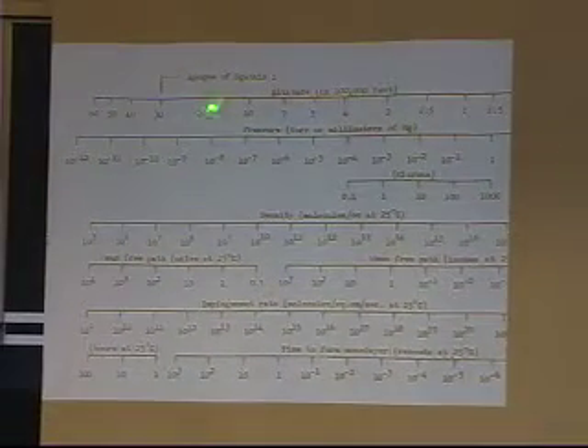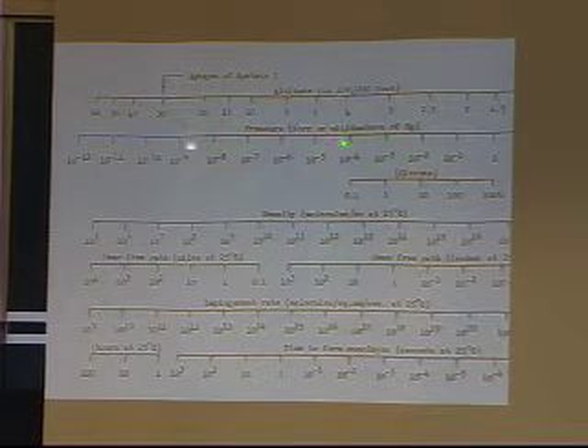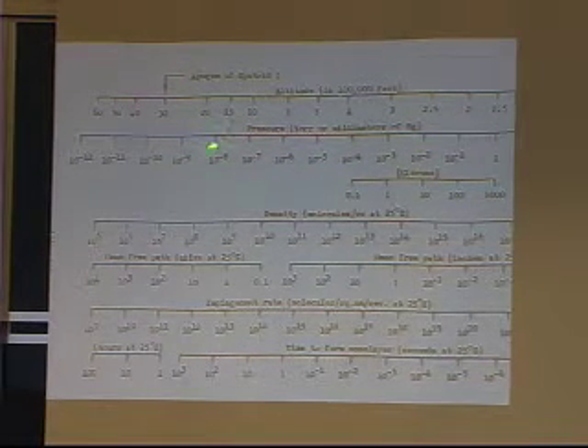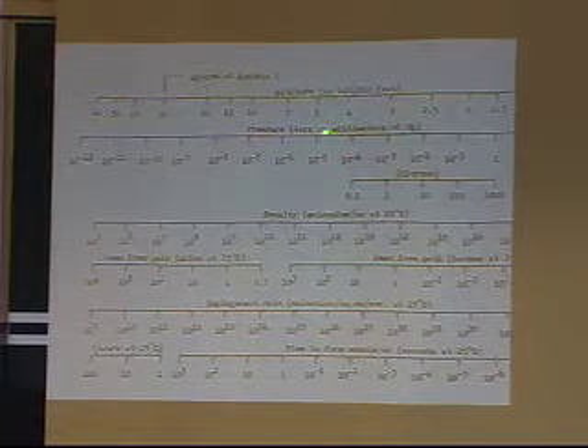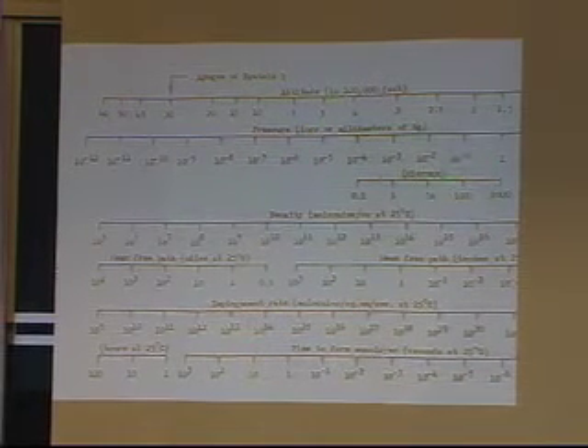They studied this, and out of this little book, they have this little handy chart that talks about variation of pressure and related quantities with altitude. This is in your handouts too. So the altitude in hundreds of thousands of feet, the apogee of Sputnik 1, pressure in torr down here at 10 to the minus 8 millimeters of mercury, or torr, depending on which one there is, microns of mercury. Density down here, time to form a monolayer at 25 degrees C.